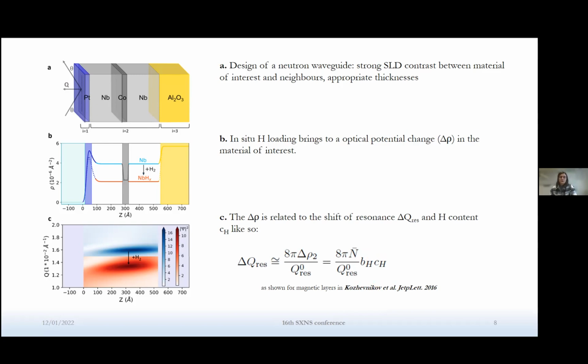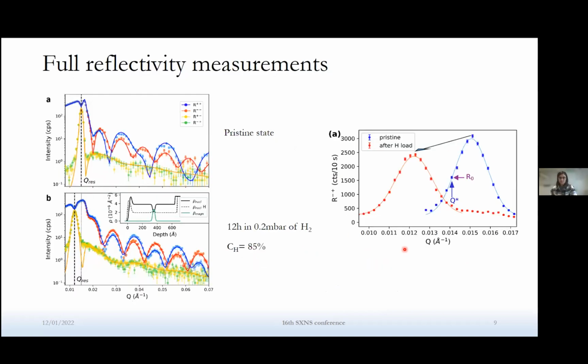So in order to have a proof of principle of the method, of course, we have done experiments. And first of all, we have measured full reflectivity curves at the beginning and at the end of the absorption process, which allowed us to retrieve the SLD profile before and after absorption. And what you see here in yellow and green is the spin flip intensity, where we observe this very strong peak, which is our resonance.